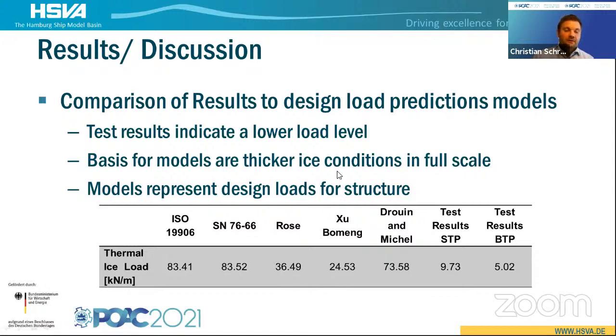We first of all then got back to our initial expectation, which loads we might have expected in which range, and compared that to different design load prediction models. And what we figured out is that our measured data is at a relatively low level, or below the level of the prediction models. Of course, these are normally made for thicker ice conditions in full scale, and also represent a design load where the structure should not break or have any issues. So of course, these ones will be conservative.